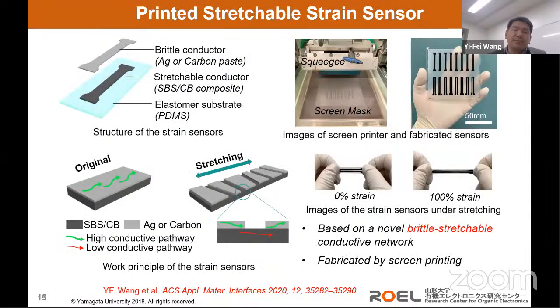And then we also developed a printed stretchable strain sensor, by using a novel brittle-stretchable conductive network. This sensor was constructed by using a silicone-based substrate, a stretchable conductor, and also a brittle conductor. And the sensing mechanism is very easy to understand. The brittle conductor layer easily generates cracks when we stretch the film. So in that case, it will give a very big resistance change, so it can offer us a very high sensitivity.